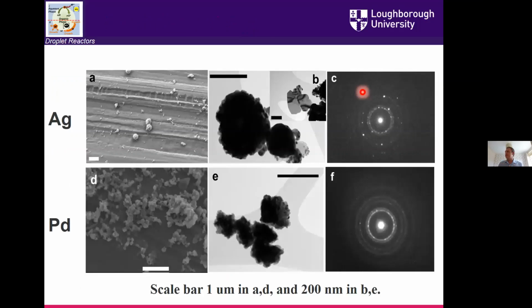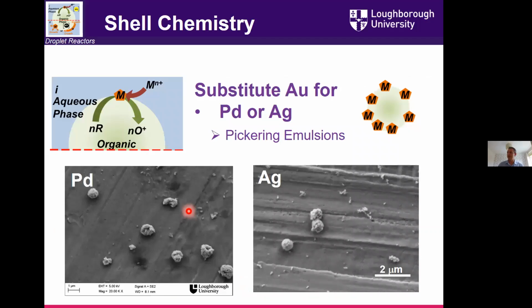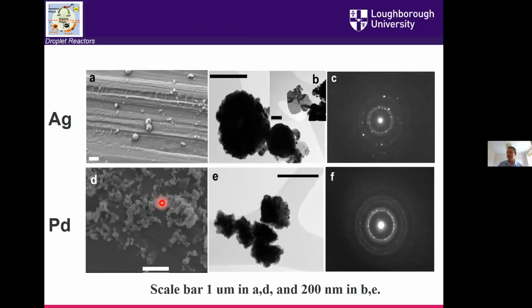And just to really show you, one of the things that we thought would happen for silver, because it has very similar growing mechanisms or preferred crystal faces to gold, is that we expected silver to give us lots of platelets in some ways. And we didn't see as much. We did see some platelets with the silver, and it certainly was more crystalline when compared to the palladium. But the palladium particles were much easier to fragment when you prepared them. So I show you this image here where the palladium particles look like nice clusters. Actually, it really depends on how heavy-handed you are or how you handle them on the SEM, because often they can shatter. And you see these clusters of smaller nanomaterials in there, which is reflected by the diffraction patterns of those. But we wanted to press on.